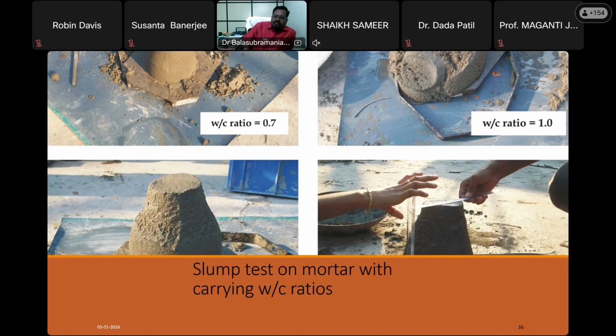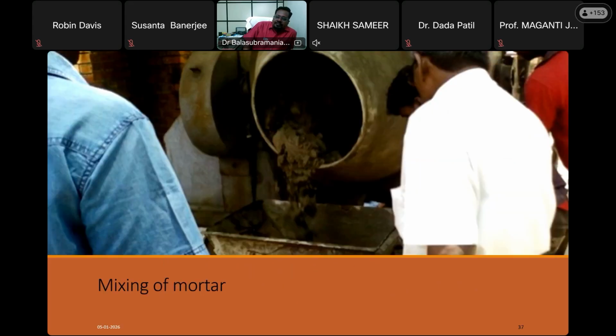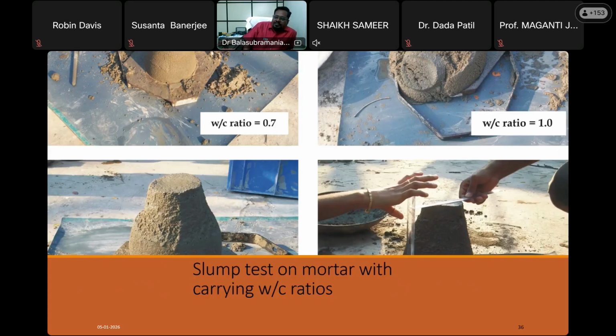Here we have carried out a flow test separately, but I have shown only the slump test. For varied water content, we have obtained that slump. Somewhere around, say, 0.85 or so, it was coming better.